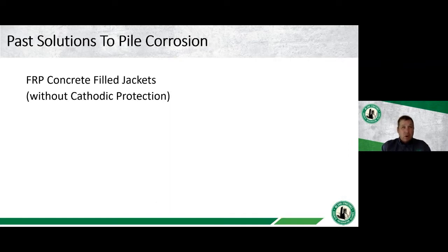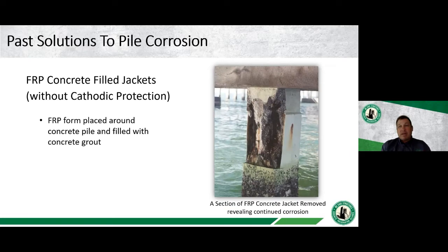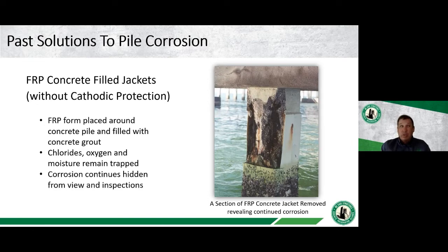Something that has also been done in the past that is very similar to the epoxy filled jackets is kind of like a mass concrete jacket. And it again is a stay-in-place fiberglass form that's placed around the pile, and then it's just filled with concrete grout. It was designed to perform the same thing that we did with the epoxy grouted jackets as well. But what ends up happening is you still have chlorides and oxygen and moisture that remain behind. And so the corrosion continues. And as I mentioned in the previous example, it's hidden from view. So you can get some pretty significant corrosion occurring under there that's not even visible to you when you come out to do a visual inspection on the jackets.